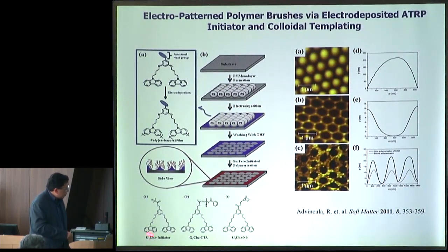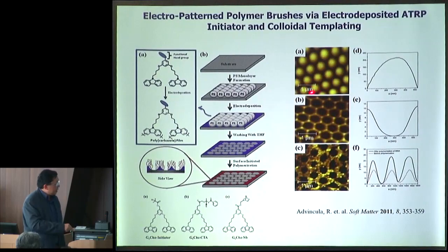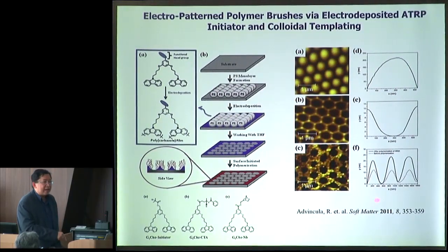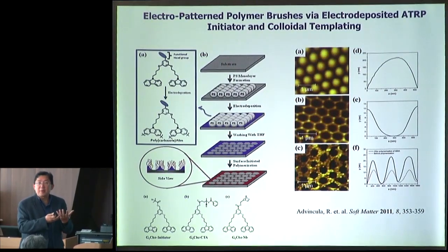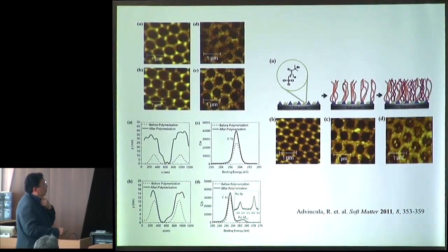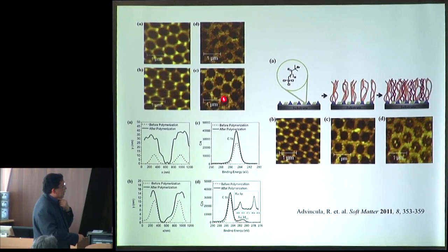So we can make macro initiators for ATRP, for ROP, for metathesis, and then after we pattern this polymer macro initiators, we can then grow a polymer brush on top of it. So as you can see here, the patterned macro initiator conducting polymers, and then after growing a polymer brush, you can see these thickened lines. Basically, the polymer brush grew on top of the conducting polymer. And then we did that on all three of them. So these are, again, examples for metathesis and ATRP.